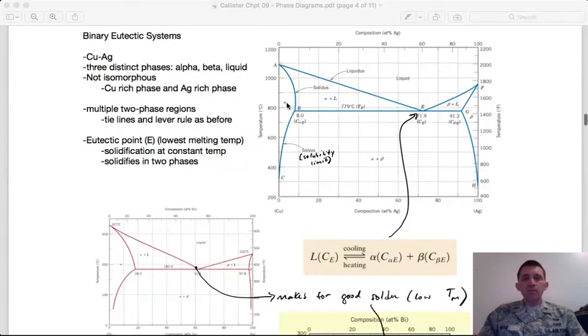And the alpha is a copper-rich phase, with a relatively low solubility limit. I can only put so much silver into copper. And then on the other side of the phase diagram, I have beta, which is a silver-rich phase. So likewise, I can only put a small amount of copper into silver. And so any composition in between is going to have a mixture of alpha and beta phases. And also I'm going to have regions where I have alpha in liquid and then beta in liquid.